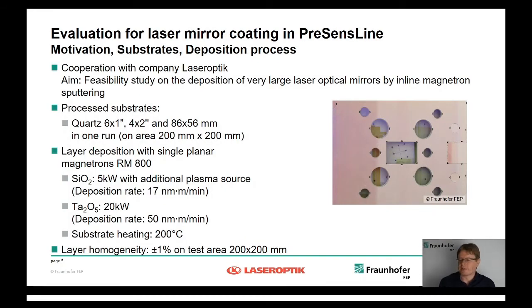Now I come to the first application, the laser mirror coating that was done in our PreSensLine machine. Here we have this cooperation with the company Laseroptik. The aim was a feasibility study on the deposition of very large optical laser mirrors by inline magnetron sputtering. The actual substrate size was much smaller, as you see here. These substrates were mounted on an area of 200 times 200 millimeters.